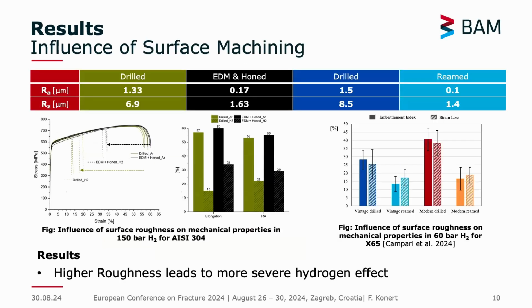With that, I want to come to what I would say is the most important point for manufacturing the specimen, because the state of the inner hole plays a crucial role for the hydrogen effect itself. On the left-hand side, we have 304 austenitic stainless steel in two manufacturing conditions. The green ones are drilled, and the black ones are EDM, so electric discharge machined, and then afterwards honed, just to get rid of the surface from the process. As you can see, for the EDM and honed specimen, you have a clear reduction in area if you load it with hydrogen, but it is not nearly as big as for the drilled specimen. You can also see that in the elongation as well as in the reduction of area.